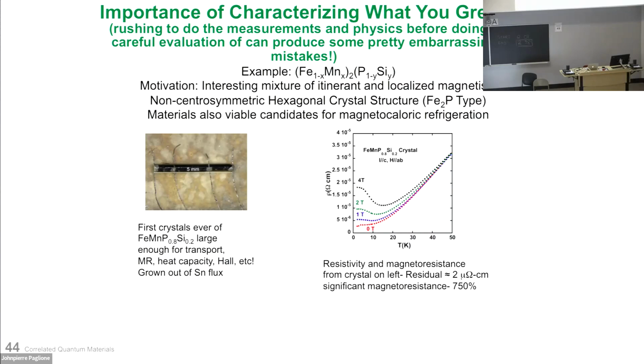The iron is diffusing through the liquid, and eventually you'll get a high enough concentration at the cold end to precipitate the Fe3Sn2. It's not as hard and fast a rule for the homogeneous temperature as standard flux. Yeah, it's an interesting technique.